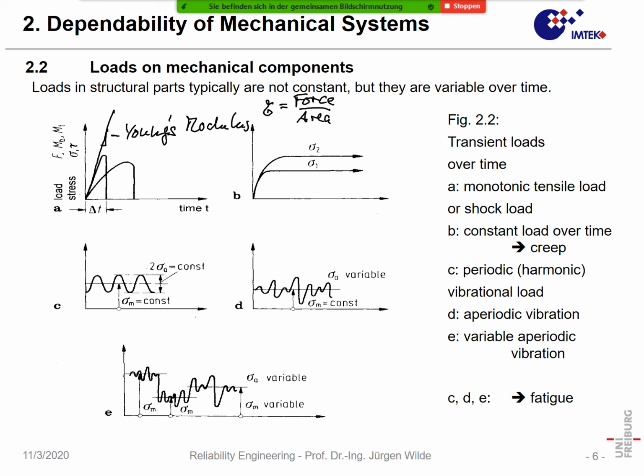What I would like to point out is that it is well established that in fatigue, the frequency of the testing or the frequency of the load is not of importance. So when you have a fatigue problem, it doesn't matter if it is at 10 hertz or at 1000 hertz. What counts is the number of revolutions or the number of mechanical cycles you have here. Of course, if you have a low frequency, it takes much longer until you reach 10 million cycles, for instance. Okay, that's fatigue, and fatigue is a result of alternating stresses in a material.